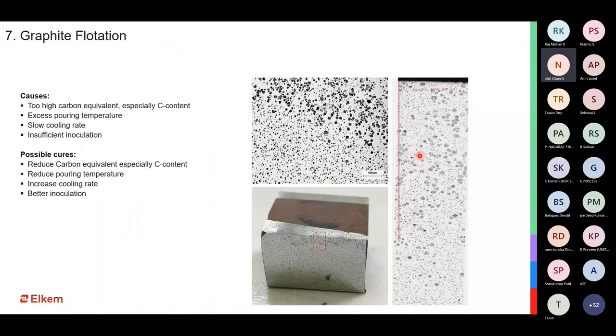This kind of defect is common in most cases only for the heavy section castings, where the rate of solidification is slow and the amount of time for the carbon to come out or float up is higher.